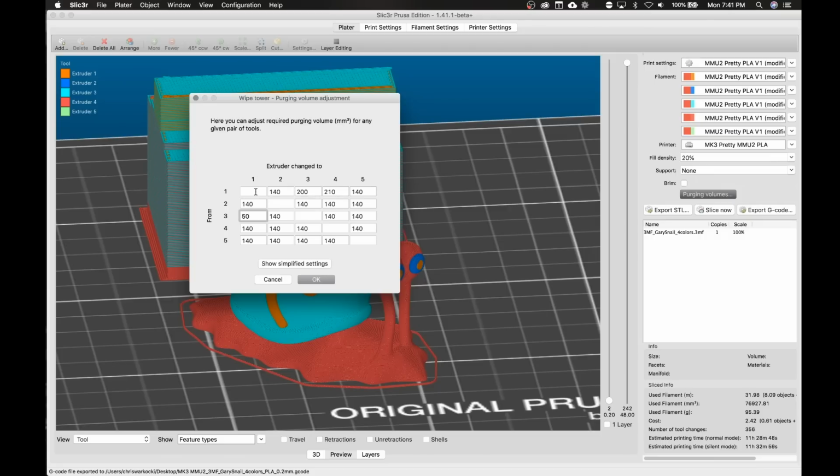And 50 actually worked out great. The black pigment in the Filamentum black is very strong, and lowering it worked awesome. And the same thing worked for my gold to black. So basically what we're doing now, instead of purging more material, when we move from tool head 3 to tool head 1, so moving from Vertigo gray to black, we purge much less.